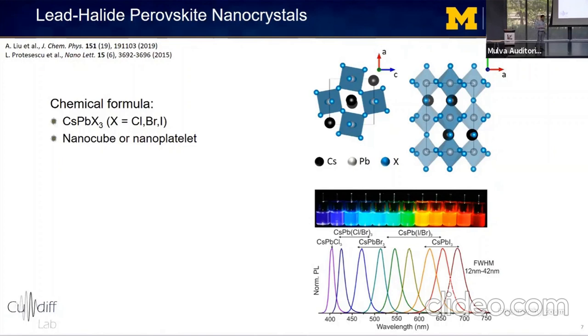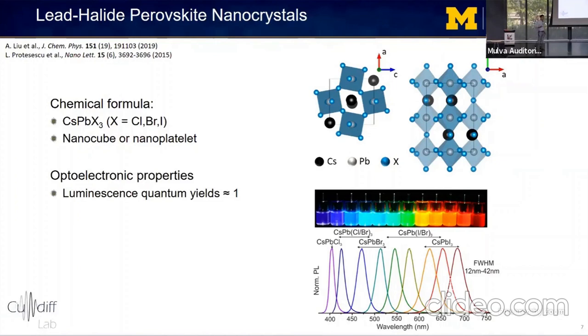And these perovskite nanocrystals have attracted tremendous attention in the nanocrystal community in recent years due to their unique optical and electronic properties. So for example, one can obtain quantum yields near unity from a bare perovskite nanocrystal without additional synthesis complications such as alloying or growth of additional shell layers on top. There's also an additional tuning knob for the emission color, which is the halide atom X. And as you can see in the figure at the bottom right, one can tune the emission color all the way from purple to deep red by changing the halide atom without changing the quantum confinement.